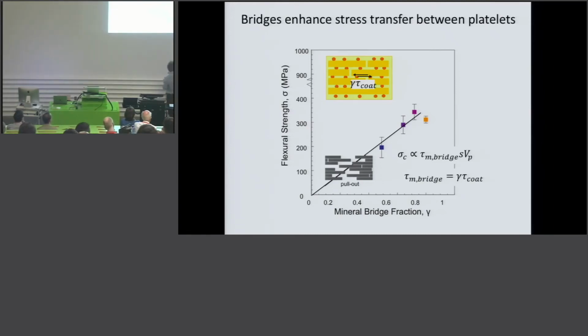And what we find is that, at least for this preliminary data that you see here, we indeed see a linear relation between the strength of the composite and the fraction of mineral bridges that are connecting these platelets. And this is this part, and we see that under these low fractions of mineral bridges, the material indeed fails under pull-out mode. And if we go higher, you start to level off the properties and you start to see fracture of the platelets, and that is because now the stress being transmitted is just too high through this high concentration of mineral bridges.